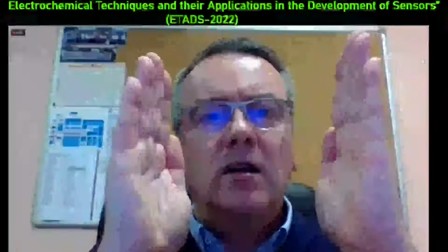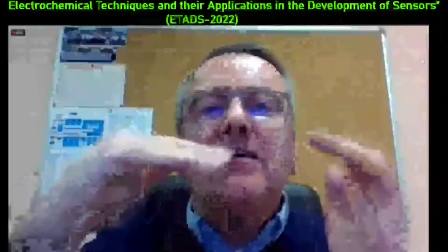In the present case, the silica walls are mechanically stable, and so the groups are physically linked and they cannot move. They just have some flexibility due to the propyl chain. The only way to have the response is that one ferrocene is close to the other one, and the electron is hopping from one ferrocene to the other one. This is the first part of the mechanism.